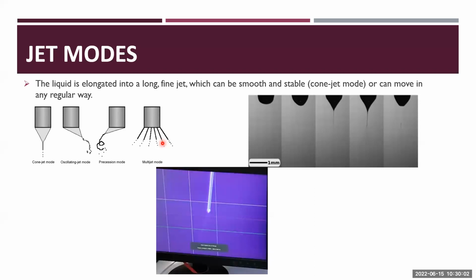You may need to increase or decrease the polymer concentration, adding a surfactant or so on to get the size you want. But in this technology, using the same formulation, we only play with the process. So meaning that we don't need to change the formulation, we just change the process. Usually there's two main variables that we need to change: the flow rate of the liquid and the high voltage